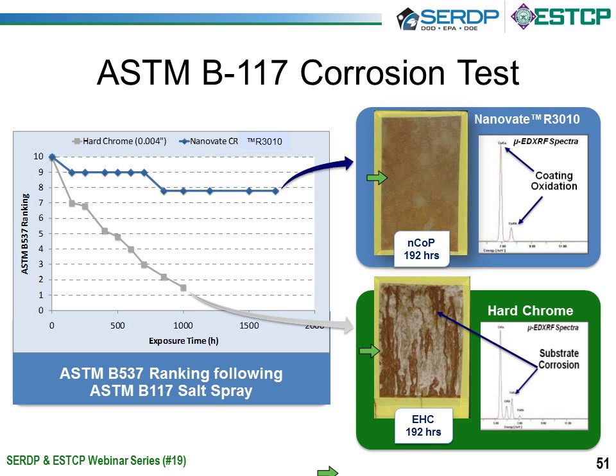From a photographic standpoint, the appearance of cobalt phosphorus coatings appears to be a corrosion product. This is much more pronounced when you optically photograph it than if you were to visually witness these. This has been documented to be a surface tarnish. It's an oxide of cobalt, and I have later in the presentation some additional work we did to confirm that.